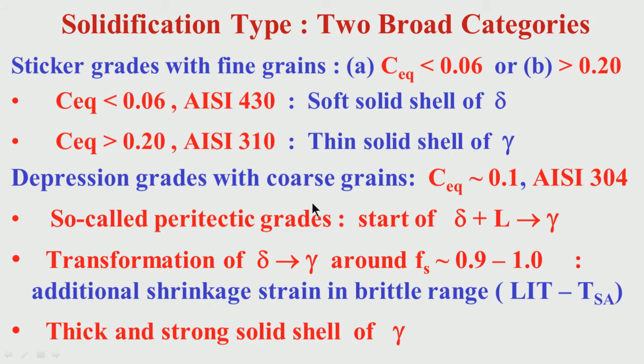Now, I have mentioned what are the depression grades, which chemistry is prone to depression. And I have also mentioned depression grade means there is a formation of air gap on the surface of the solid shell. So, the heat transfer comes down, so the coarse grains, coarse dendrites become more coarse. So, what are the chemistry ranges? Where the carbon equivalent is around 0.1 for low alloy steels or plain carbon steels, or for stainless steel 304. So, these chemistries are prone to depression and coarse grains.